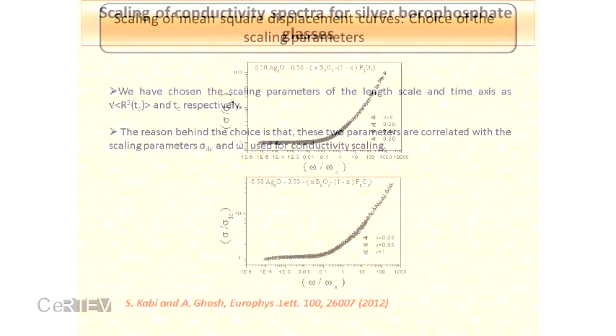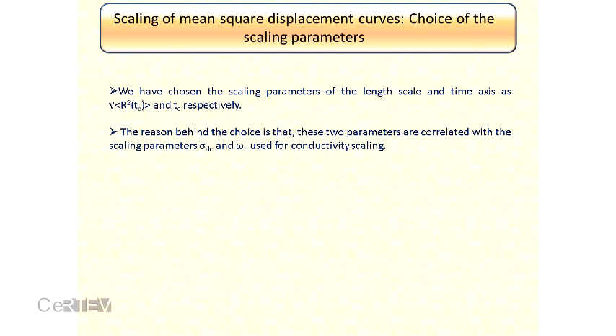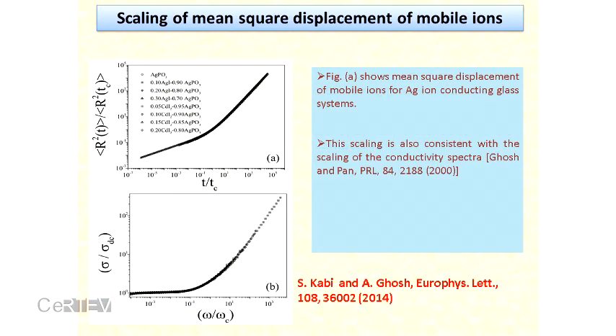Now, I have also recently developed one scaling model, which depends on the microscopic length scale of the ion displacement. And the model is very simple, you can see. I have scaled the displacement by the displacement at the crossover time, and the time axis by the crossover time. You can see a perfect superposition for a number of glasses.